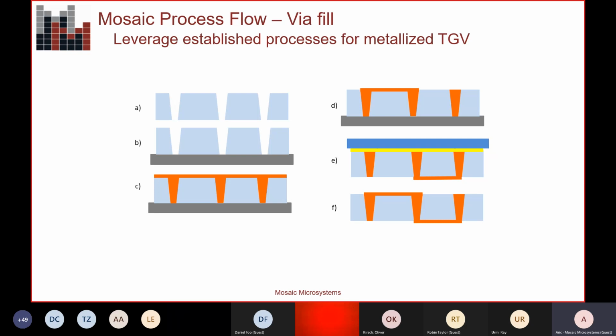One of the main reasons you'd use the more standard temporary bond technology on the top surface is that our layer is so thin, once you add topography or roughness to that surface, it's much harder to do the bond. So you'd want the forgiveness of the organic adhesive to do the backside metal. If you're doing a Damascene type approach, we believe we could use our process for the backside, but that hasn't been done yet. Basically, if you have a good, smooth, flat surface, we can bond to it. So that's a very high-level flow of how you'd leverage our technology to enable thin glass, and then ultimately you'd debond and have your device.